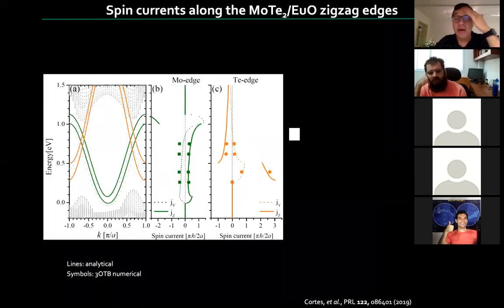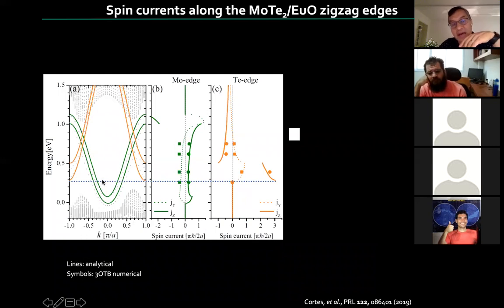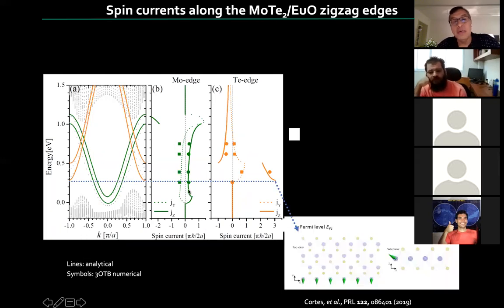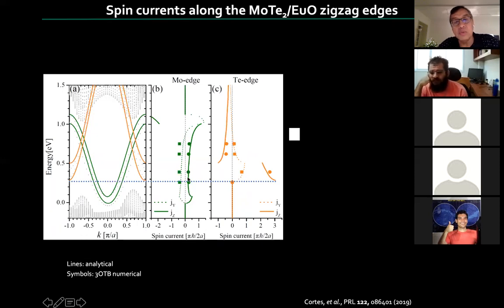So here the experiment we have in mind is to look at current, right? So apply contact. And again, imagine this is the schematic of the bands that I showed you, spin split. Now you can imagine gating the material in such a way that you put the Fermi level there. As I mentioned, the bulk will be insulating. You'll have only the states around the Fermi level conducting at low temperature. And what's here on the right is a calculation of the current that appears on the green side, which happens to be the moly edge.